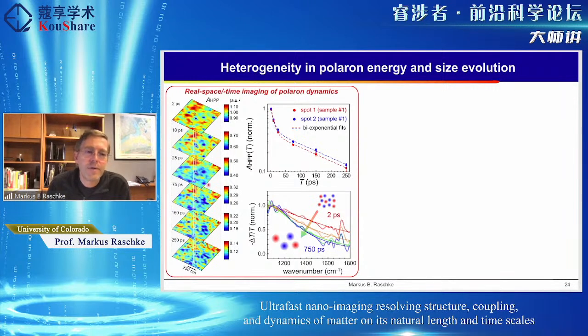Then there's a number of phenomena we can extract if you do point analysis of different time slices of different spatial locations as a function of time. Then we can probe the decay and again the spatial heterogeneity of the decay of this polaron dynamics. An alternative interpretation is also to think of this as a Drude relaxation. There is actually still considerable uncertainty in the question whether these are really polaronic or whether this is a more Drude-like carrier relaxation or a combination. But then you see that there is a non-trivial bi-exponential decay dynamics, and this is in fact a result of a fairly high density of polarons excited, which then relax through polaron-polaron scattering. So there is an excitation carrier density dependence, which can be analyzed.